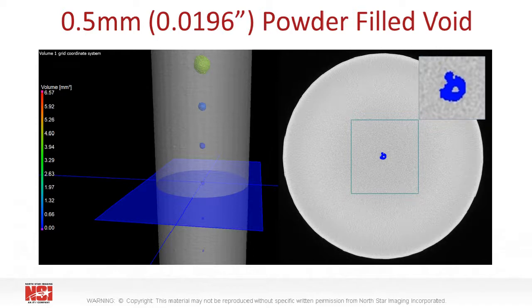This is a CT slice of the RQI insert at the 500 micron defect position. We can clearly see that the defect is not fully spherical, and there is a section in the center that is approximately 120 micron in size that is likely fused powder.